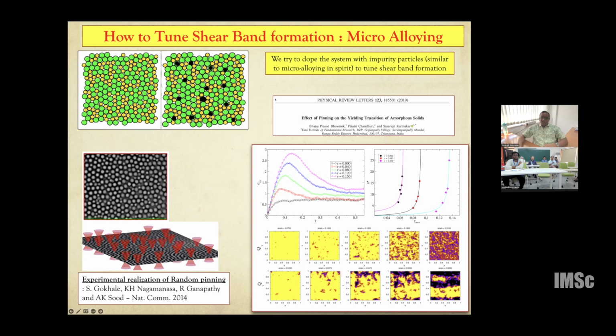And what we found, which is displayed, I hope you can see my mouse, in this panel where we plot stress versus strain, is that when you increase the degree of pinning or the pinning concentration, the material becomes much stronger. The modulus goes up significantly. The stress peak goes up, but the peak becomes broad as well. Also notice that the yield point shifts to larger strain. So the system was able to support much more load than usual non-pinned glasses.